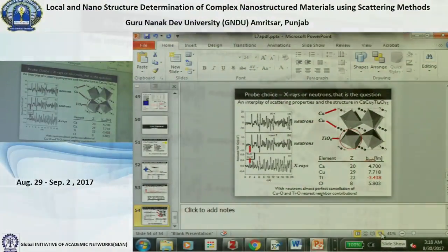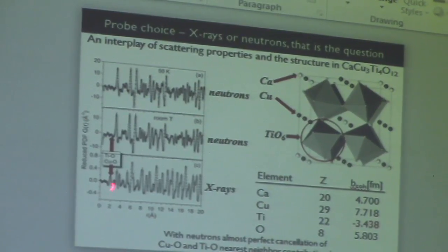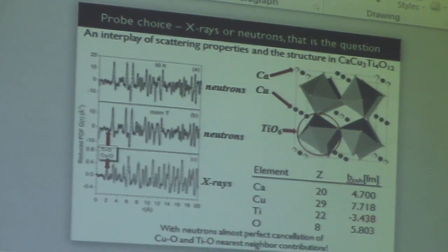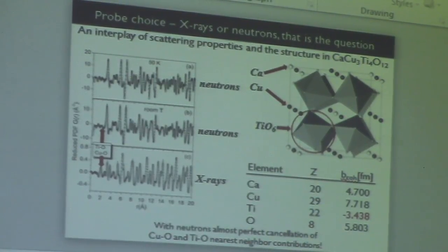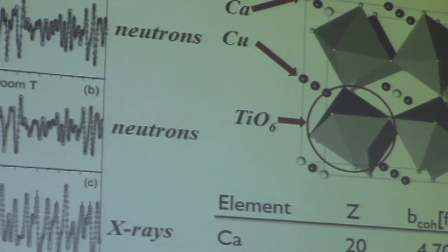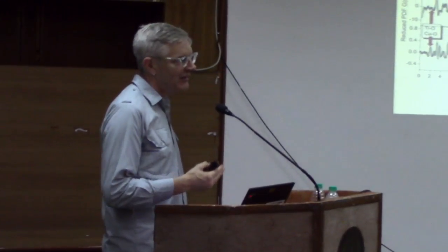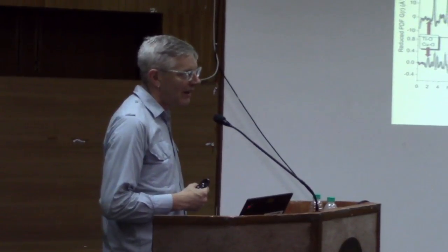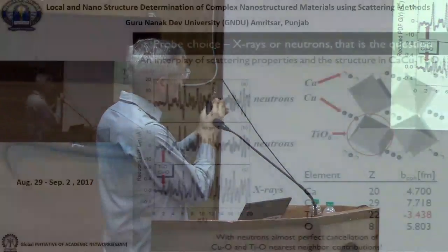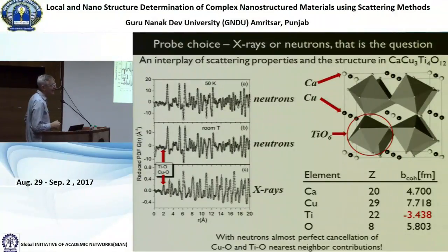So that's a very good question. It actually turns out that we have different definitions for these correlation functions. This is G of R, and it's a correlation function. A correlation function tells you the deviation from some average, right? So you have some average behavior, and then you have some deviations from the average. With this particular definition for this function, we set the average to be 0. And so the deviations always oscillate above and below 0.